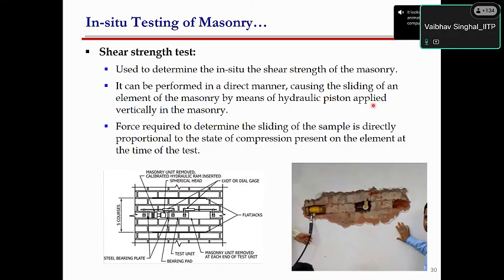The next test which you can use, which is quite important, especially for the seismic evaluation, is the shear strength test. The in situ shear strength can be found out using a test called a Shove test. In this test, you can see here, we remove one brick from this end and another brick from behind. The pressure jack is placed here, and then the middle brick is pushed. At whatever force this brick slides, that force you can call the shear strength or sliding capacity of the masonry. So this is also a simple test which can be done easily.